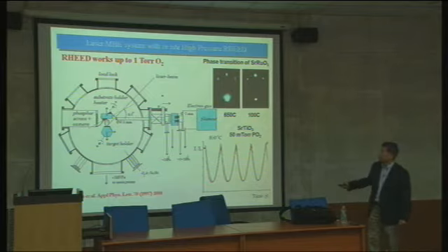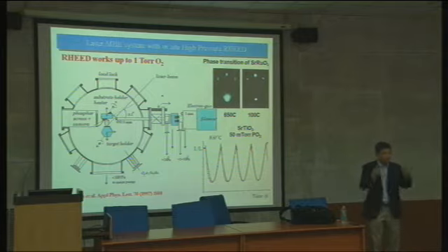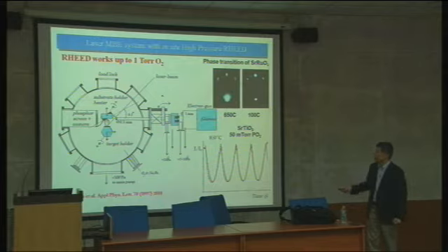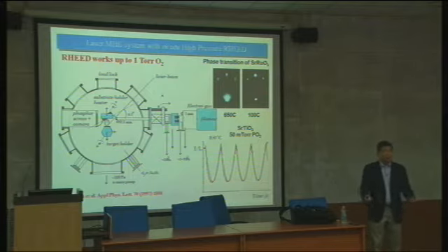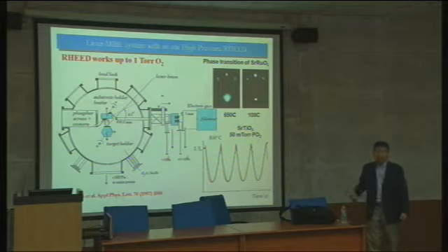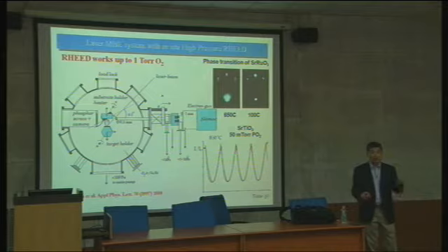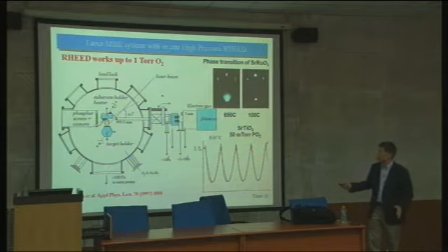Basically, you have pumping of this chamber, so you have additional pumps evacuating this region. There are two different pumps that maintain a vacuum of 10 to the minus 6 torr or lower inside this region, while in this region you can maintain close to 1 torr of pressure. So between 1 torr and 10 to the minus 6 torr, your differential pumping ratio is roughly 10 to the 6th. You need a large differential pumping ratio because you have very small tiny holes, and the additional two-stage pumping keeps this region a good vacuum.